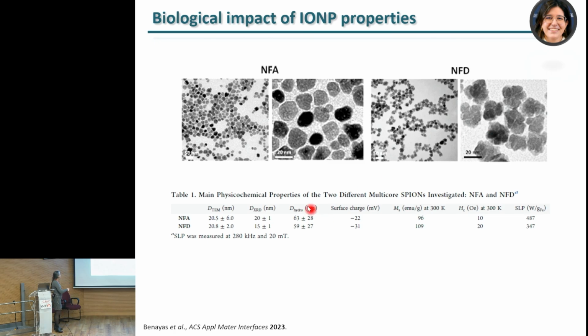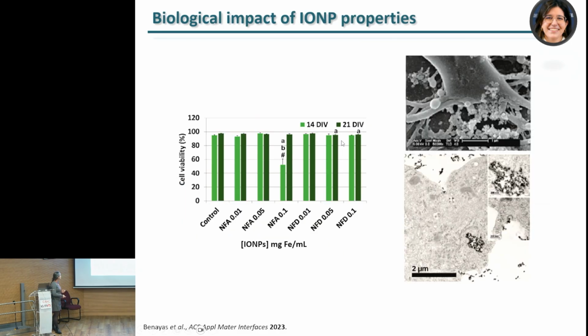You can see here both, the NFA that we call, they have been synthesized in an autoclave, so a confined system where you can control more in detail all the parameters of the synthesis, and then the open traditional co-precipitation system that we call them NFD. So these, you can see from the pictures, are more multi-core-like, these nanoflowers, iron oxide nanoparticles, but in here, the more efficient heating made them to become more like single core nanoparticles. In here we have the properties, and yes, there are differences, specifically more in the magnetic properties because of this more efficient sinterization of the cores.